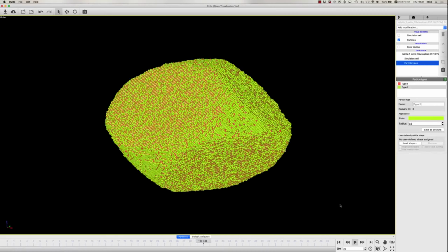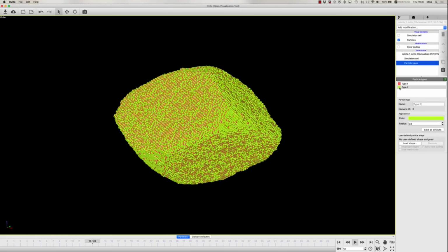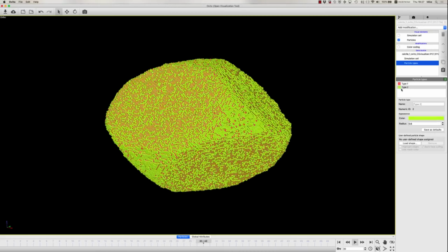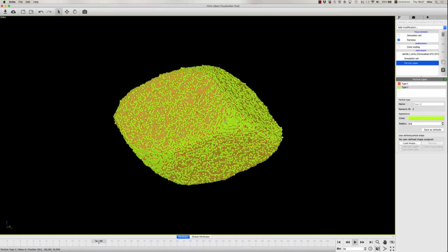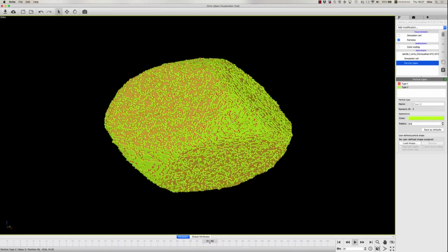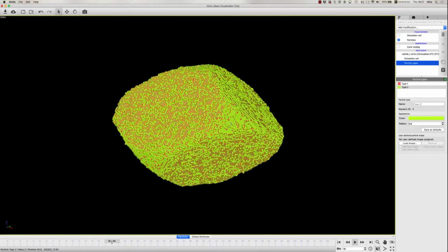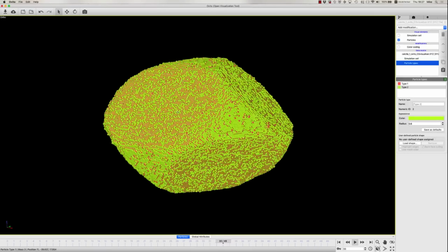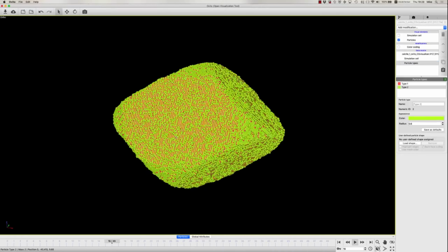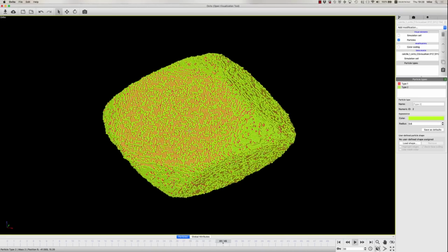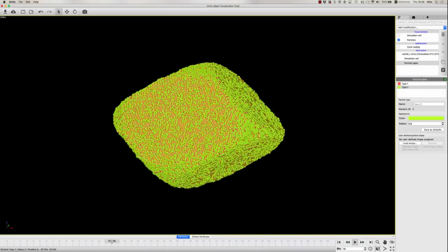So now we're just color coding according to particle types. The carbonate is red and the calcium is this yellow color. You can see that the facets which we're developing here are the polar facets, which are more or less purely covered in calcium, whereas the previous facets which we had here are the ones which have a stoichiometric amount of calcium and carbonate in, and now we're forming these polar facets in the crystal.